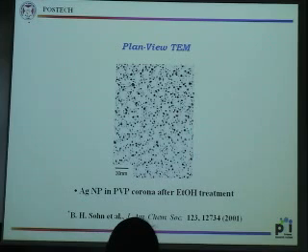So now we can think, if the amount of silver nanoparticles is above the percolation threshold of conductivity, we can get completely different conductivity before and after the solvent treatment. Before treatment, the silver nanoparticles are in the isolated phase, so we don't get conductivity. But once they come into the continuous phase, we can get conductivity. But unfortunately, the amount of silver nanoparticles is far below the percolation threshold of conductivity. Thus, we decided to synthesize the conducting polymer in the domain of PVP.